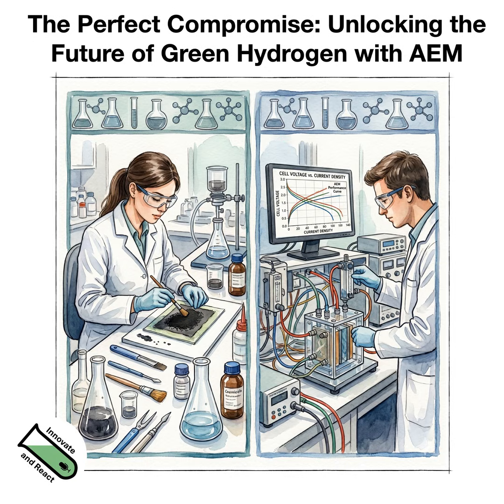This is one opportunity for the fabrication methods. In our case, we deposit the catalyst layer directly on the substrate, because the AEM membranes are difficult to handle, so it's not common that we do the CCM, catalyst coated membrane, fabrication like in the PEM electrolysis. In AEM electrolysis, we do not see the need to increase the anionic conductivity, because we still use 1 molar KOH solution in our system, and this increases the conductivity, and there is no need to coat the catalyst directly on the membrane. It's also possible to have the layer on the PTL and get quite high performance.